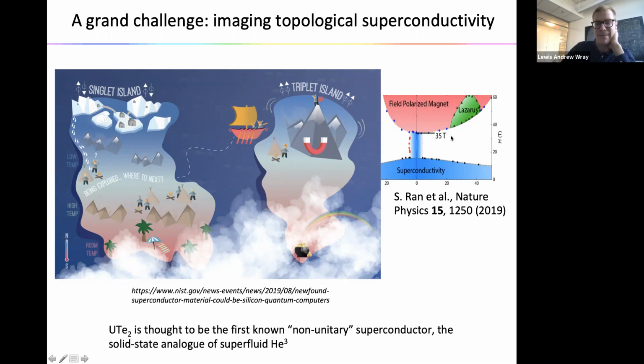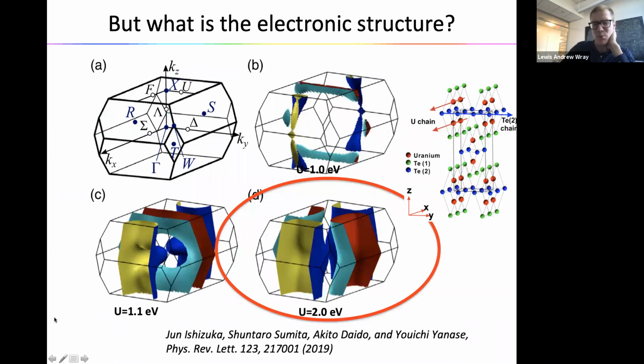But we conducted an initial study on it using ARPES a year and a half ago, and that came out last year, in which we found that the electrons in it are quasi one-dimensional. So we were just taking a picture of the energy versus momentum contours of the electrons, and we found that the states only have velocity in one direction, but they're quasi one-dimensional in 2 different directions.